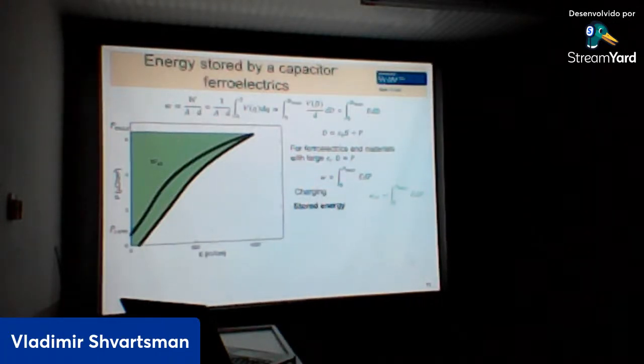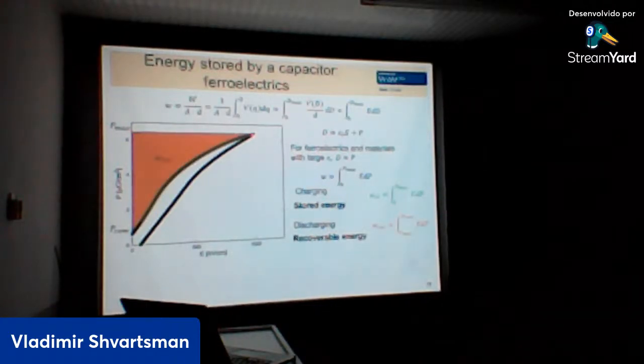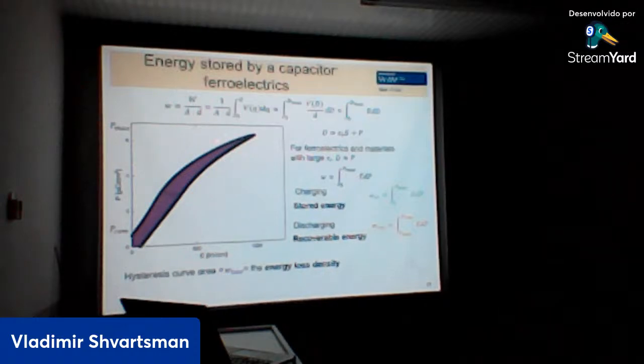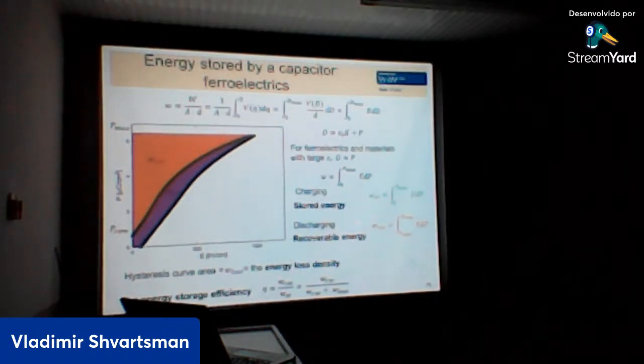But when we now discharge our dielectric, you see that the energy which we obtain is smaller. The energy between the discharge branch of the curve and the polarization axis is called the recoverable energy. So we have stored energy and recoverable energy, which is less, and the difference is given by the area of this hysteresis curve, which is nothing else than the energy loss density. One can consider the stored or recoverable energy density, and also consider a parameter called energy storage efficiency, eta, which is the ratio between recoverable and stored energy. When eta is close to 1, it's the optimal case: all stored energy can be used again.